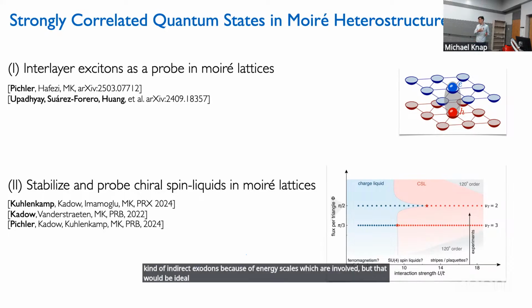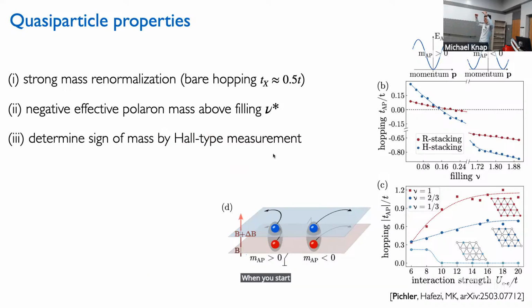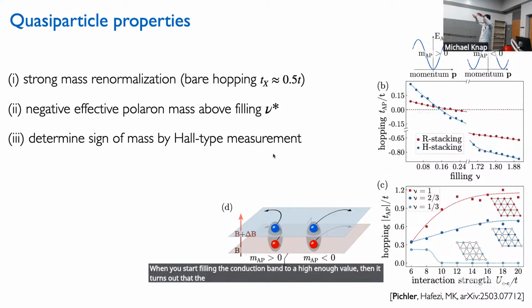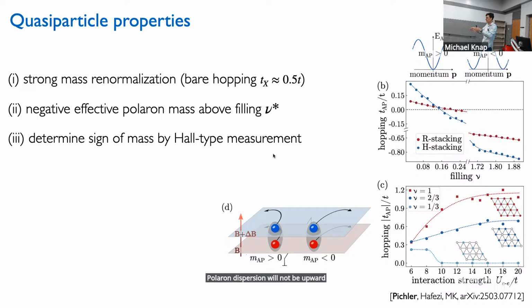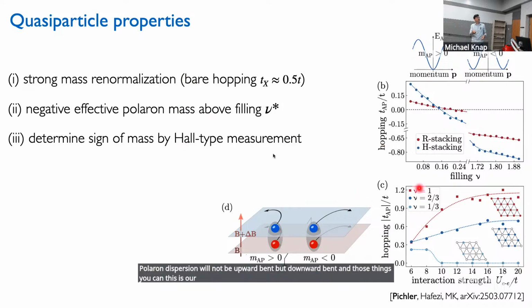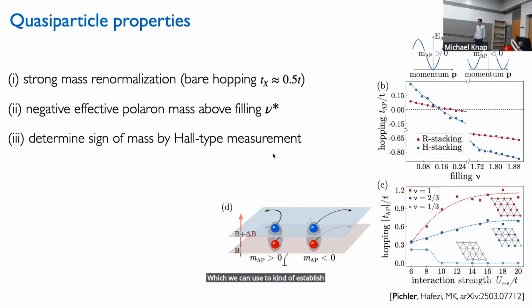Or, to test more of our predictions, for instance, the exciton formation here, I glossed over it, but maybe I can just go back to it. It turns out that when you start filling the conduction band to a high enough value, the mass of the exciton will be inverted because the electrons have a negative mass. And this will have consequences, right? So the polaron dispersion will not be an upward band, but a downward band. This is our prediction from this model. And those things you could measure in Hall type measurements, because Hall type measurements pick up the sign of the mass, essentially, of the charge carriers which you are measuring. So those are little bits and pieces which we can use to establish more and more this effective picture.